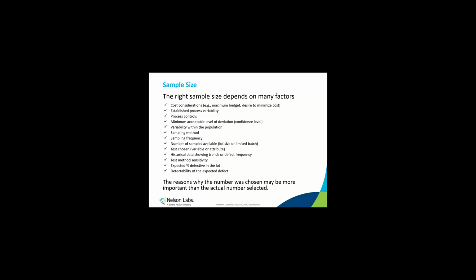The method sensitivity and the expected % defect in the lot are also considerations. If you're expecting a high defect rate, then a smaller sample size would detect it. But if the defect rate is low, then you would need more samples to have a chance that one in your set is defective. If the expected defect is easily detectable, then there's a higher probability of finding it. If you're using a sensitive method that has a high probability for detection, well, maybe you can use a smaller sample size.